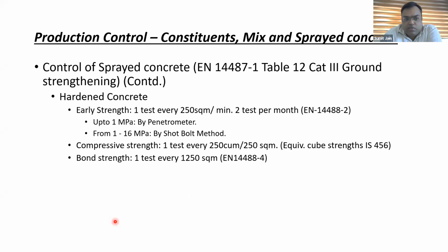Next, we move on to the hardened concrete. The previous one was the fresh stage. Now we have the hardened stage. In the hardened stage, we have early strength, which we discussed earlier, like up to 1 MPa by penetrometer, and 1 to 16 MPa by Shot Bolt Method. And the frequency of this early stage strength is one test every 250 square meters or minimum 2 tests per month.